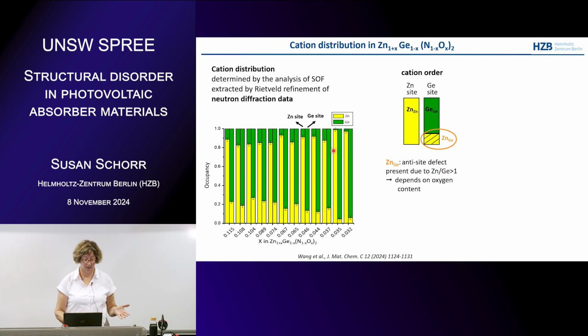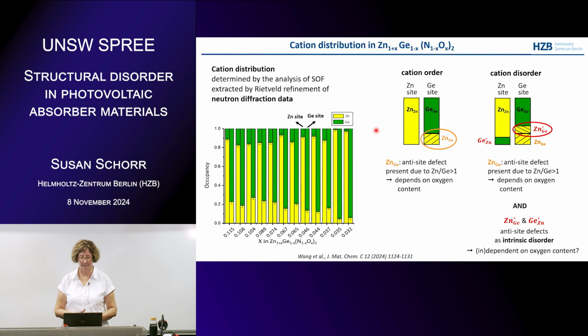But you can see here from the figures that on the zinc site there is always something green everywhere. So that means we have more a situation like that, that a part of the germanium is on the zinc site and a part of the zinc is on the germanium site, coming on top of the zinc on germanium antisite we have due to the off-stoichiometric composition. And this, with the stars, we call the intrinsic disorder. So the Zn_Ge star and Ge_Zn star antisite defect is the disorder we are looking for.